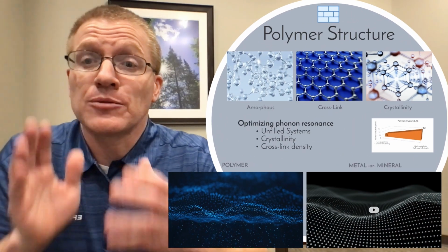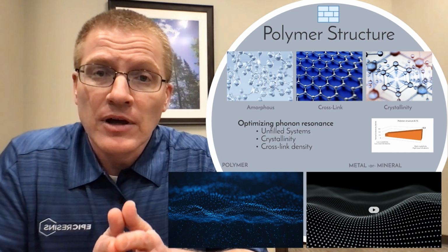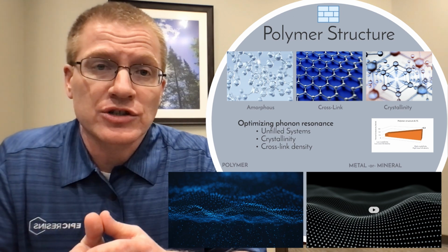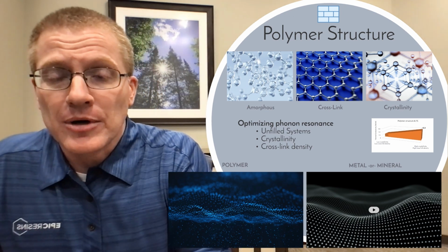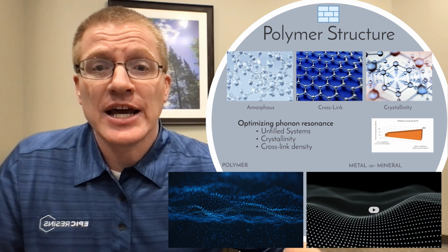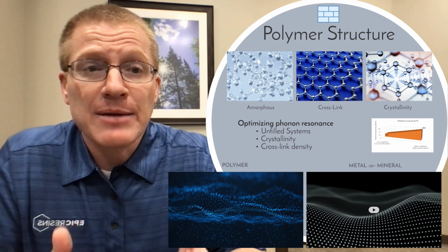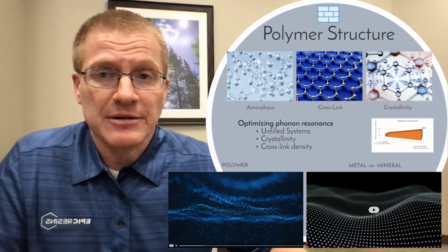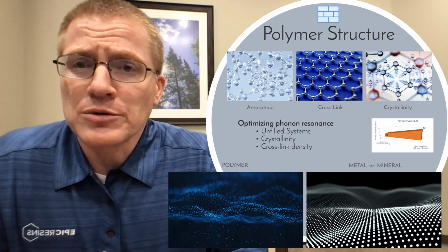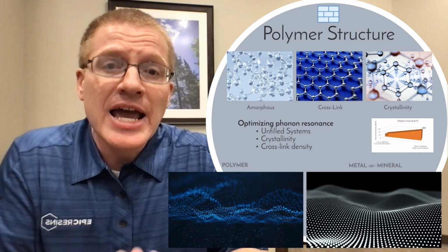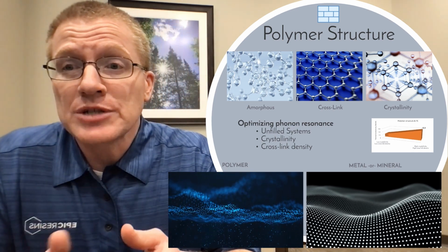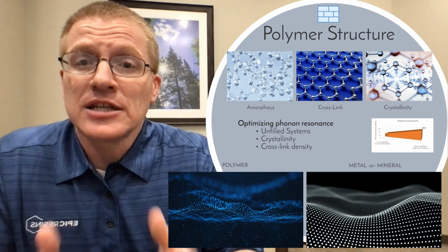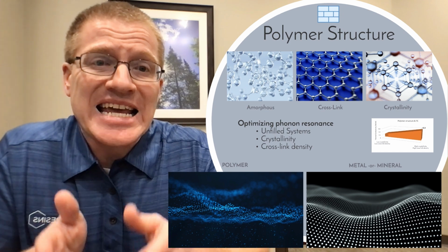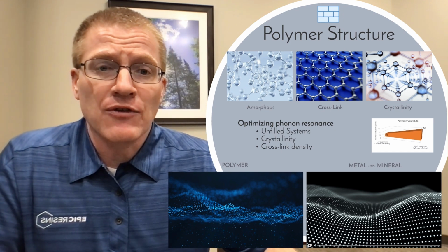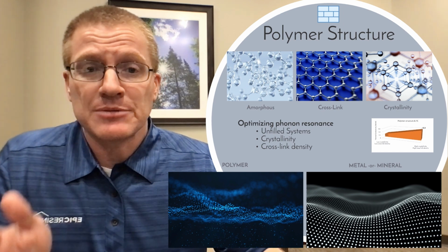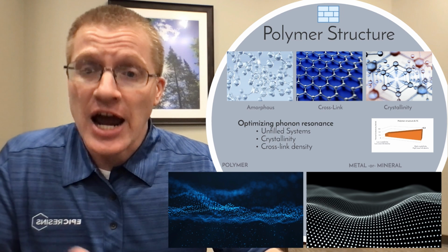We formulate at Epic Resins from a molecular structure to property relationship. Ultimately, we utilize our knowledge of molecular structure and the properties it imparts in the final polymer. Many polymers have an amorphous structure that tends to hinder phonon resonance, as we discussed and demonstrated in these videos that I played in the previous slide. When we build a more uniform structure in the polymer, we improve the molecular kinetics and phonon efficiency. In polymers, we do this by increasing crystallinity and cross-link density in the molecular structure. This improves phonon resonance and hence thermal conductivity. In these images of amorphous, crosslink, and crystallinity, you can see the differences between that amorphous structure, cross-link structure, and having higher crystallinity.